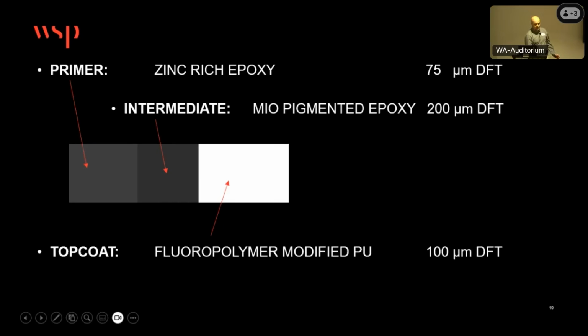And we have found that in practice, this fluoropolymer top coat appears to be a lot tougher than the polyurethane, a lot more impact resistant, and it presents itself with a very glossy and slippery surface, which is advantageous in terms of preventing dust and dirt accumulation, which then enhances the durability of the paint film.